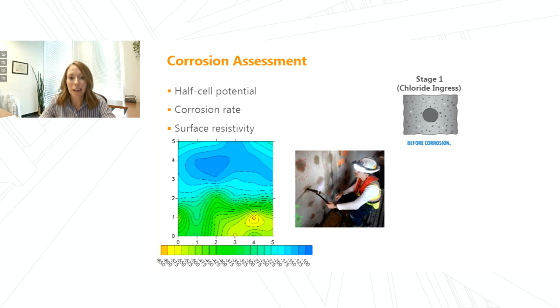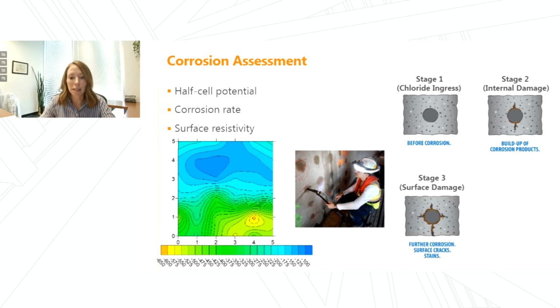The best example of this that I can give you to understand when we're talking about reinforced concrete is chlorides. Like Scott mentioned, chlorides are everywhere, so this is a pretty common issue. But when we talk about chloride ingress, we have a reinforced concrete element, we have a chloride exposure, and as those chlorides migrate to the level of the reinforcing steel, we get depassivation of the reinforcing steel, which provides a buildup of corrosion product, and that induces tensile stresses in the concrete, and it causes cracks. As we get additional buildup of corrosion product, the cracks continue and propagate to the surface of the concrete.